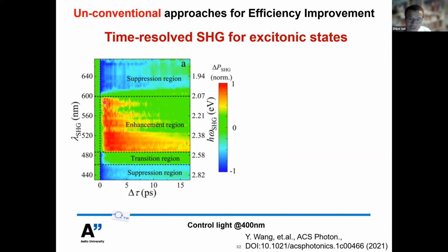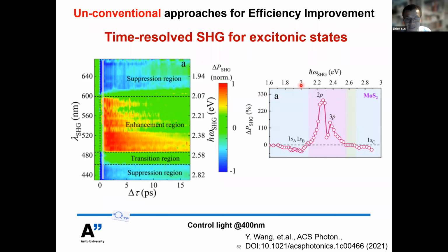Then if we plot the modulation at a fixed delay around 1 picosecond, we can get this modulation depth as a function of the different second harmonic generation wavelengths. Here we can easily correlate the peaks at the different enhancement states and also the suppression regimes with the different excitonic states inside of the MoS2.